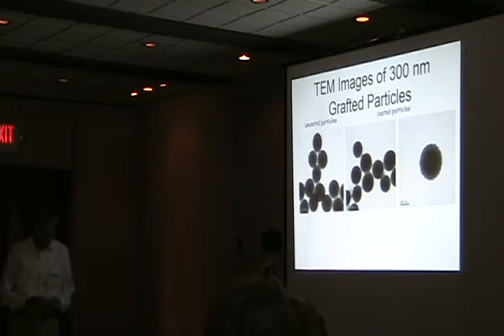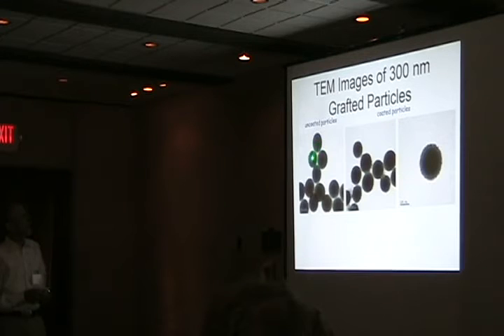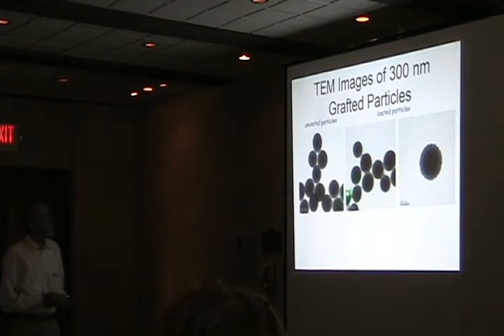Okay, if you look at the glass beads we start with, and these are, I guess, 300 nanometer beads, you see they're very smooth. And when we coat them by growing the polymer on them, you see the surface becomes much rougher. It's very easy to see this with transmission electron microscopy. You can see they even tend to stick together.